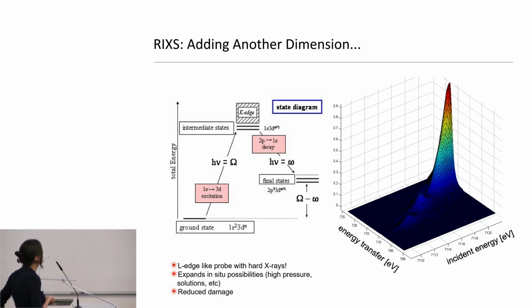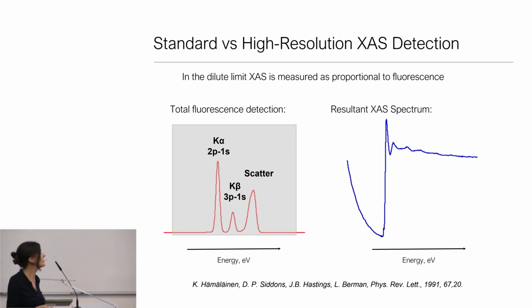has been very interested in is to combine X-ray absorption and emission together in what is known as resonant X-ray emission, or RIXS, where we have X-ray absorption on one axis and the emission event on another. And so, for instance, you could do a 1s to 3d excitation, follow it with the 2p to 1s decay, and here the difference between the ground state and the final state is actually the equivalent of an L-edge. And so there are lots of ways to play games with the selection rules and the experiments.